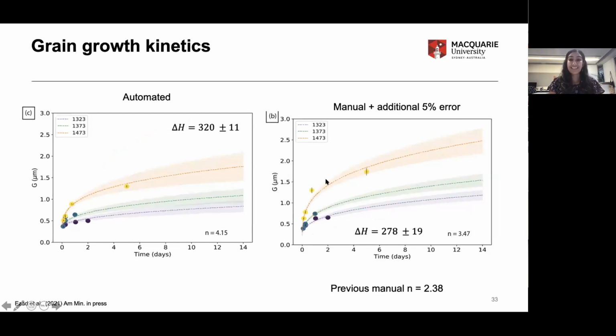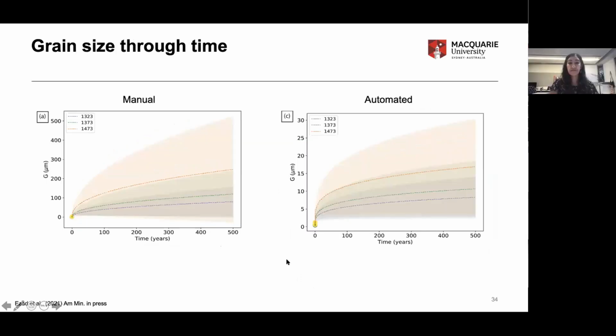Once I added in the additional 5% error between me and my supervisor, matters became even more complicated because the grain growth exponent changed again. So now I had 3 different grain growth exponent values. So what does that actually mean? Well, for a period of 500 years between manual and automated techniques, it means that the grain size is an order of magnitude different. So even though I've constrained the grain growth kinetics and I've been able to find parameters which make geological sense, the grain size overlaps in size, temperature, and time.